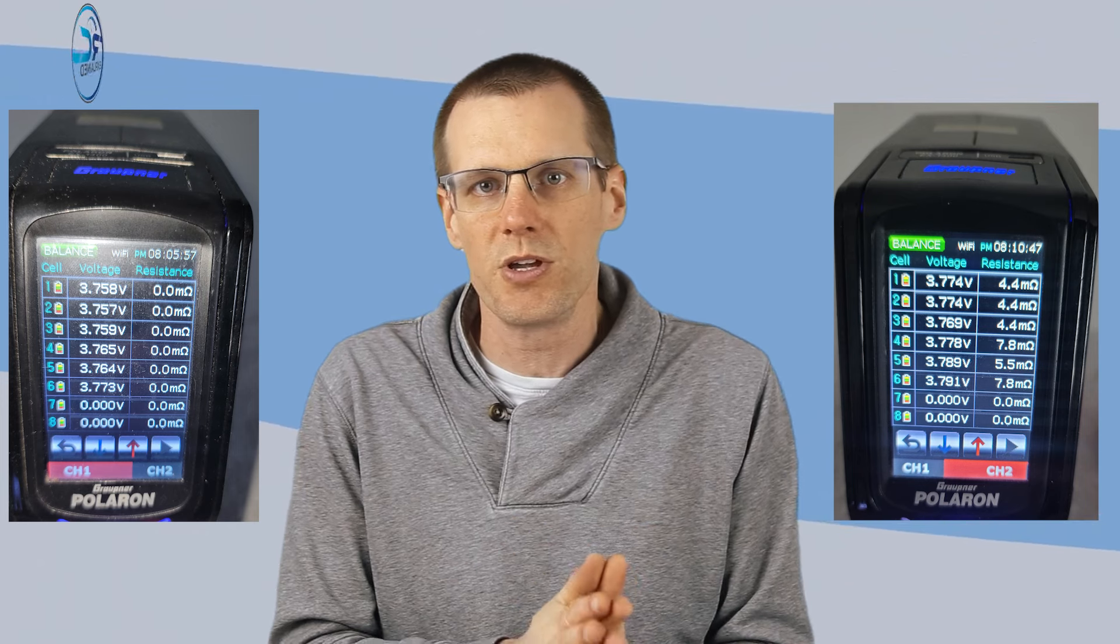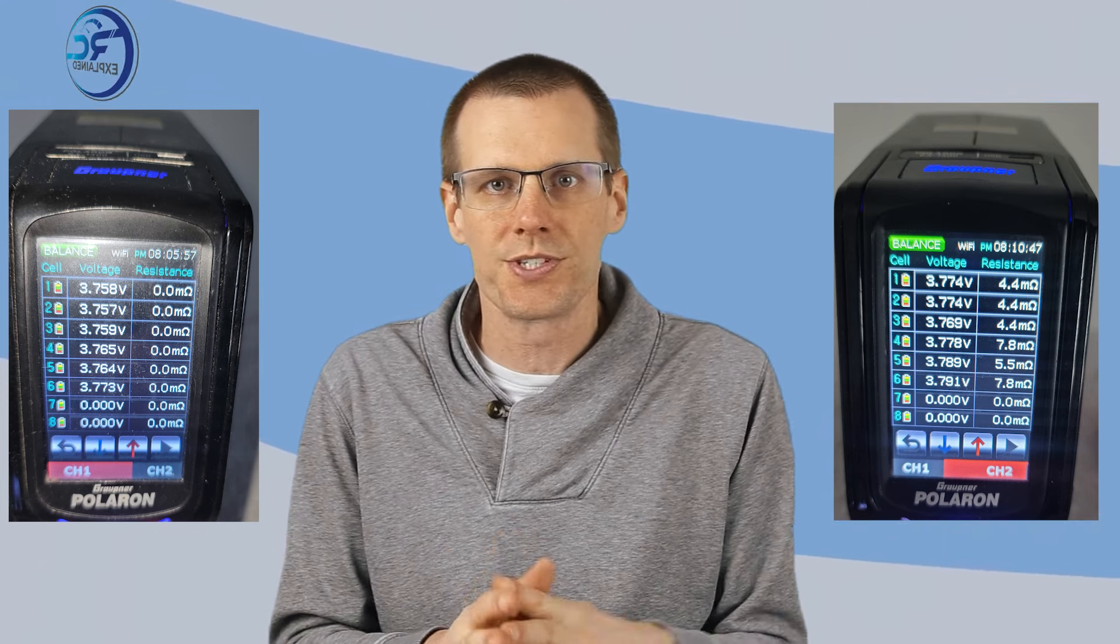And ultimately when it comes to looking at the resting voltage, a weaker performing battery will have a higher resting voltage. And this is because we have some gas left in the tank, so to speak. The results that we got here, I'll throw some images up on the screen, we got anywhere from 3.75 volts resting voltage all the way to 3.79 volts in terms of resting voltage. So both of these values are not so great when it comes to the actual resting voltage of the battery pack.